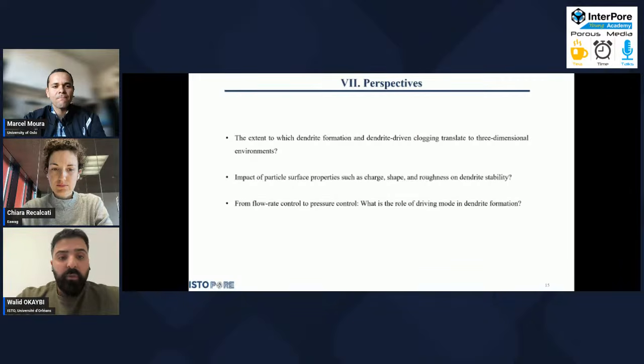And as perspectives for this work, we would like to investigate the extent to which dendrite formation and dendrite clogging can translate in three-dimensional environments, like in column experiments. We would like to investigate the impact of particle surface properties such as surface charge, shape, and roughness on the stability of these dendrites. And as we did our experiments at a controlled flow rate, what would be the effect on the dendrite formation if we did that at controlled pressure?